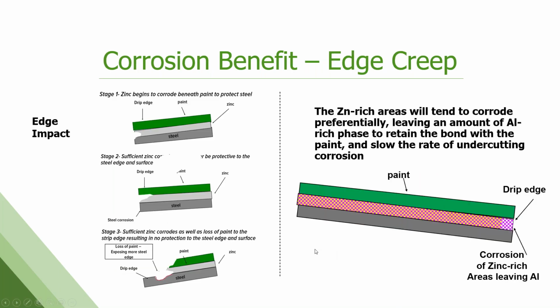Same with a drip edge, a cut edge, same phenomenon, right? So over time, corrosion of that zinc on a galvanized product wears away. Now you have an overhang of paint there that's not attached to anything. That's going to come off, exposing more zinc, and you're caught in this sort of vicious cycle that just propagates over time. Whereas with the aluminum zinc product, again, you're left with this aluminum lattice work there, which is keeping the steel protected, but also allowing the paint to adhere to something longer than it would on another substrate.